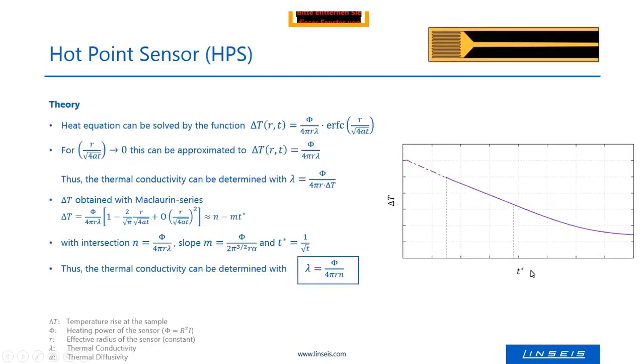Show this again. This T star is 1/√ of time. And then you get a curve like this. So long times are in this direction to the y-axis, and short times are here. This is the beginning of the curve. It needs a little bit until you get a stable signal, until the heat goes through the sensor and reaches the sample. And after a couple of seconds, you see a linear increase here.